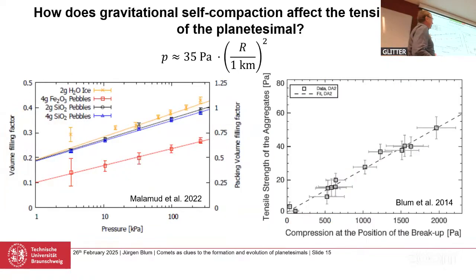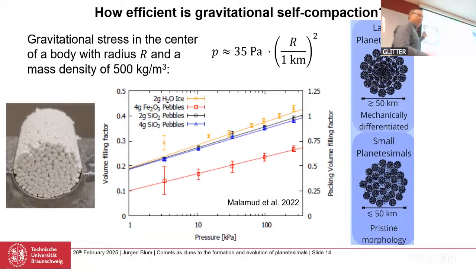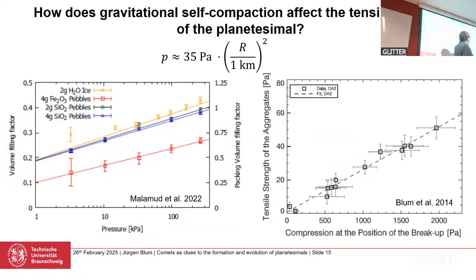So again, the same plot here. Back in 2014, we did experiments with pebble piles like those and compressed them. And with the same pebble piles, we measured the tensile strength, which is shown on the y-axis here, as a function of the compression. Now 1 kilopascal is here. So again, the formula, a 10 kilometer body would be 3.5 kilopascal. So 10 kilometers would be here. So we're in the 1 to 10 kilometer body range, where the pressures are little.